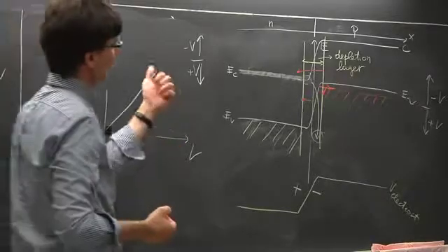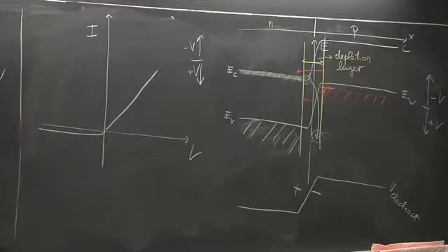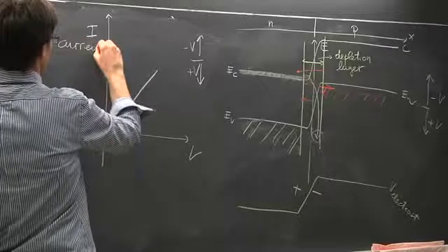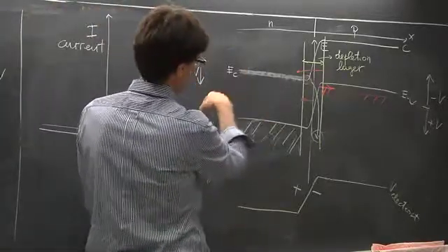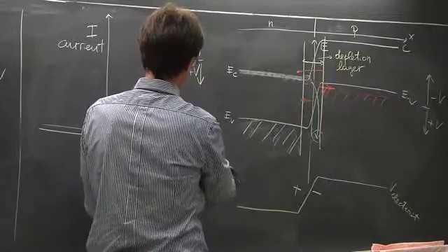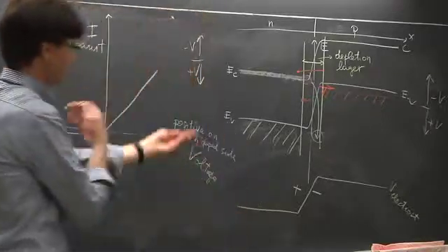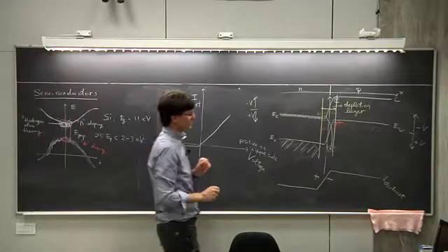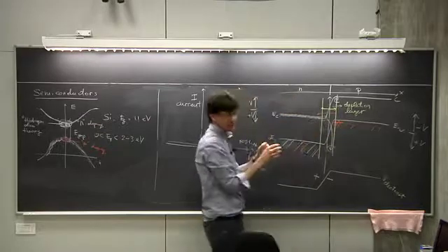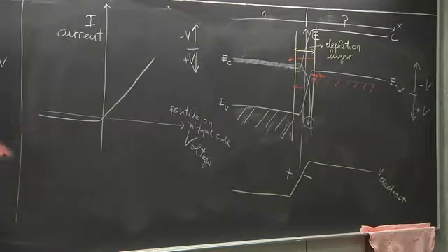So when I apply a voltage which is opposite with respect to the previous one, because of this asymmetry in the position of the band structures, I'm going to have a current which is extremely low. Now I'm plotting current, right? It's current versus voltage. And I'm assuming that plus means plus on the left side, on the n-type. Okay, so positive on n-doped side. This is what I mean by positive. Otherwise, it's just reversed. So I have two completely opposite situations. If I apply a voltage that increases this level with respect to this one, then I have standard conductivity, because charge flows without problems. If I do the opposite, that is, I lower this band with respect to this one, there's no more possibility for flow of electrons. There are no available states that can flow from one side to the other one of the interface. So the current will be essentially zero, will be very small.